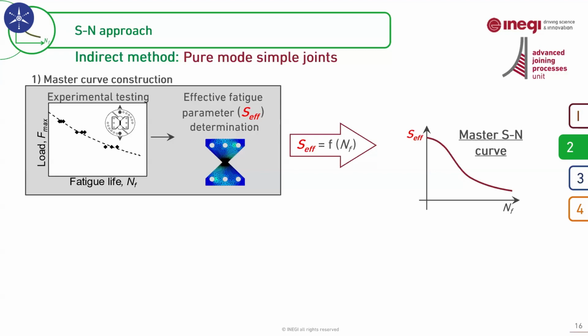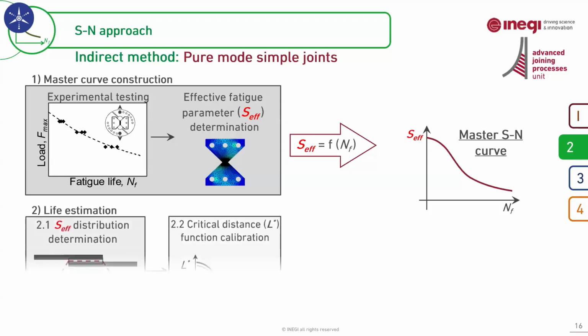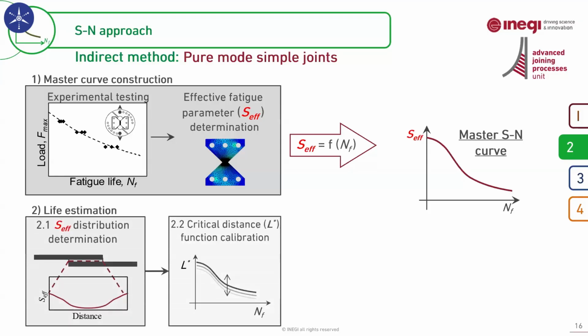Once the master SN curve is obtained, a finite element analysis of the actual joint should be performed, and the fatigue damage parameter S-effective here can be extracted from FE results. And by using the master SN curve, we will be able to predict the fatigue life of the real joint. But please be careful, because here we are talking about prediction and not obtaining the real value. This is another important difference between indirect method and direct method.